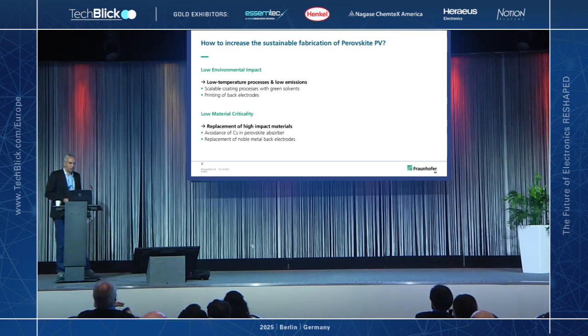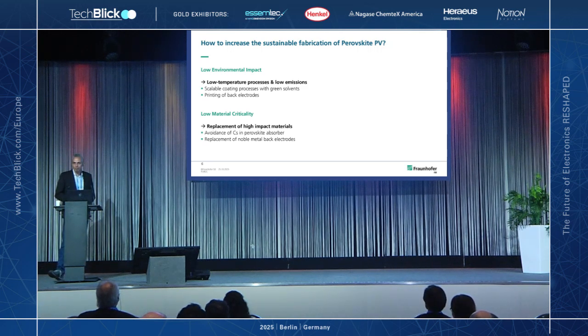And this list might not be complete, but our approaches are we want to make sure that we can, in principle, fabricate these devices with a low environmental impact, which means we want to apply low temperature processes and low emissions during the fabrication. And our approaches here are scalable coating processes with green solvents and printing of back electrodes, not evaporation of metal electrodes. And secondly, the low material criticality, which we want to address, where we want to replace obviously high impact materials. For example, we want to avoid cesium in our perovskite absorbers, and we want to replace noble metal back electrodes. And some results on this I will show you in the next couple of minutes.